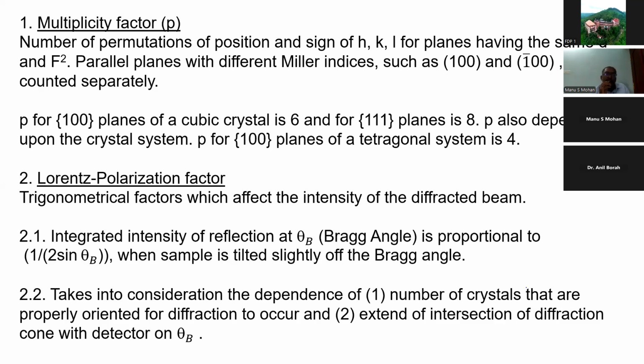Then you have Lorentz polarization factor. This is actually a product, arising due to trigonometrical factors. When theta is very small, you have many planes which are closer to the Bragg angle. The diffraction cone - we often think of it as two-dimensional, but actually a three-dimensional cone is produced. This cone's intersection is higher at lower angles, which can be imagined easily.